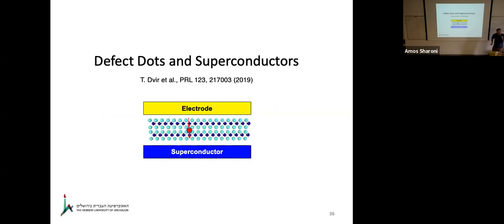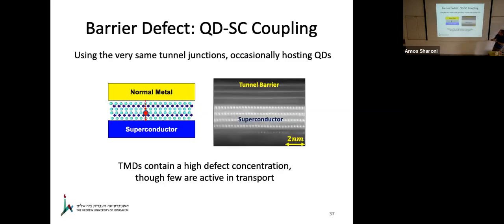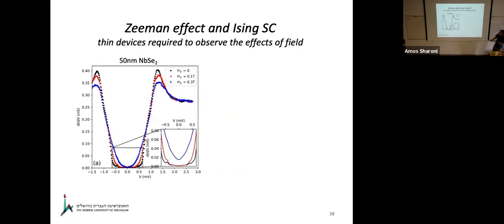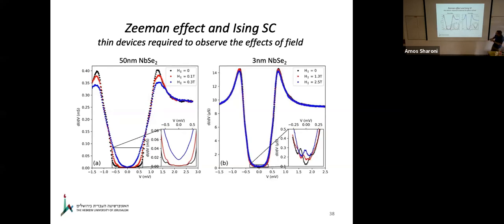Now, remember, I said the superconductor can survive into very high in-plane field. That makes it possible to characterize the defects, and I'll show you why. Again, this is the structure: a superconductor, a normal metal, and there's a defect in the barrier. We measure the spectrum and we see little squiggles in the transport way inside the gap. If we look at the data on a very thin niobium diselenide and zoom in very carefully, we see these subgap states.